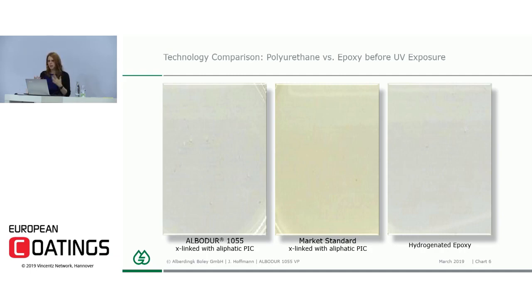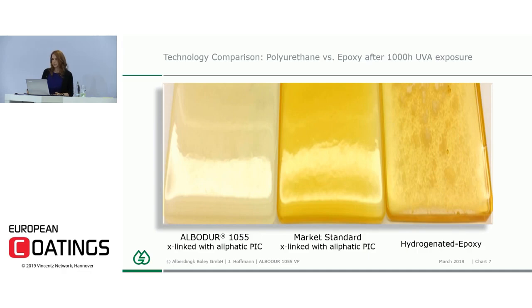MDI makes the system quite hard. The polyol has to make the system soft in order to balance that behavior. So when we have aliphatic PIC, we have already a soft hardness. So that means the polyol has to come up with a performance of hardness and tensile strength. So we did that over the adjustment of the polyol and the different molecular weight, and exposed these 3 samples to 1,000 hours QUV. And as you can see, we have a tremendous color difference. The market standard also has very dark sides. That is coming from the yellowing under the very, very hot temperatures in a QUV machine. That means 1055 is also UV stable, plus it is thermo stable.